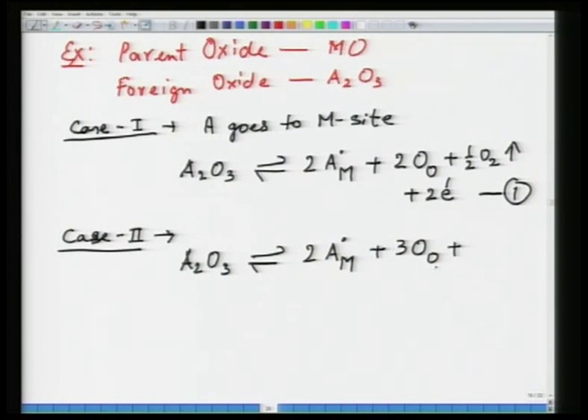So, for these 3 O sites you need 3 M sites, and you are filling only 2 of them, which means one of the M sites would be vacant. So, you will have V_M with 2 negative charges. Now, this is balanced site and mass wise as well as charge wise. So, this is another possibility that could happen when you put A2O3 impurity in MO solid.